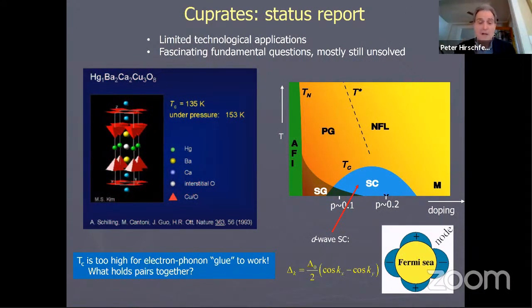So where are cuprates now? There are many papers on cuprates, and the field is still very lively. Most of the issues that make it lively nowadays, I'm not going to talk about. The superconductivity, ironically, is probably the easiest phase of the entire phase diagram to understand. Cuprates have a semi-universal phase diagram. They start from an antiferromagnetic insulator, that's AFI. When you dope them, they're sometimes a spin glass phase, SG, but more prominently a pseudogap phase, where you see a gap in the spectrum, but the system hasn't done any easily identifiable long range order, a crossover to a strange metal or non-Fermi liquid phase, and eventually a metal, it's believed, at high doping.